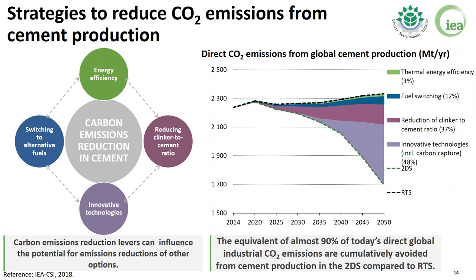So in this graph, you can also see the relative contribution of these four families of strategies in terms of the reductions of CO2 emissions for cement production, on the direct CO2 emissions, more specifically in this case. You can see that specifically reduction of clinker to cement ratio and innovative technologies, including carbon capture, are the key leaders, let's say, in terms of the impact on CO2 emission reduction. Cumulatively, the reductions in emissions between the RTS and the 2-degree scenario represent almost 8 gigatons of CO2, which are almost 90% of today's direct global CO2 emissions in the industrial sector.